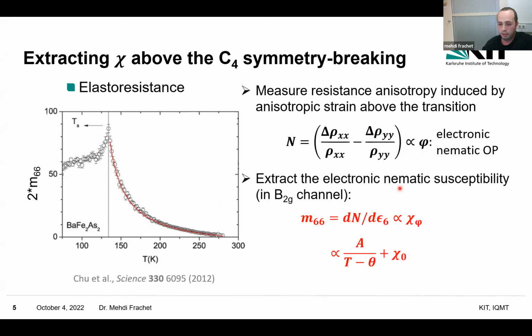They studied the response to strain in the elastic limit, and extracted this m66 elastoresistance coefficient that belongs to the B2g symmetry in the tetragonal state. This elastoresistance coefficient is directly related to the electronic nematic susceptibility. And you see this very beautiful Curie-Weiss behavior that extends well above the nematic transition.